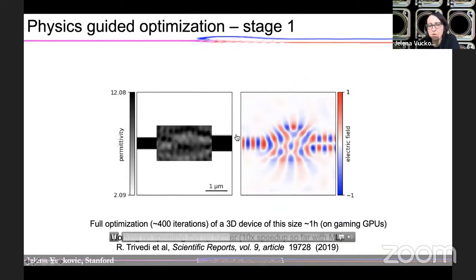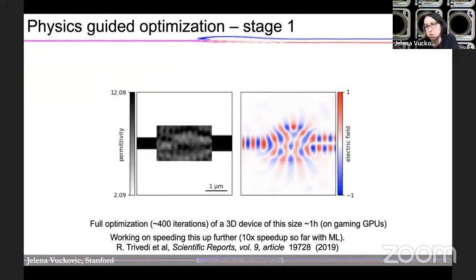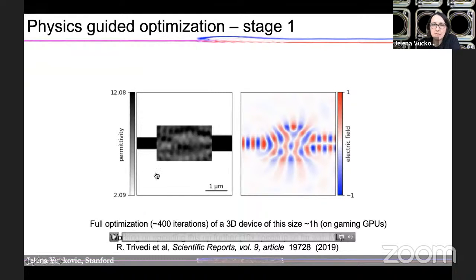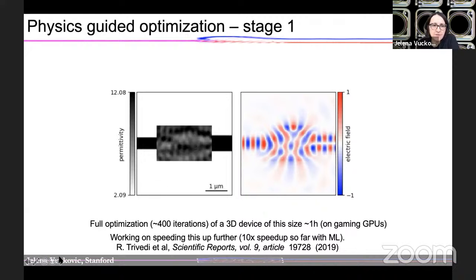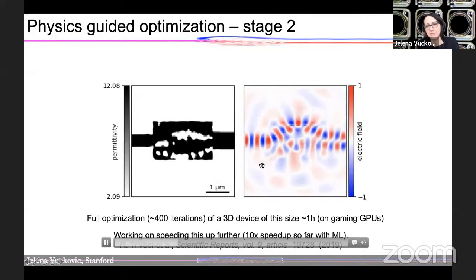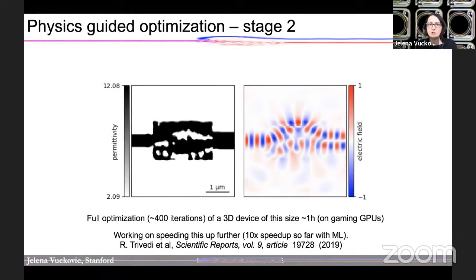You're converting first order mode to second order mode in a very small footprint, like 2 by 1 micron, much smaller than an adiabatic mode converter that people would typically use in photonics. And you see that this works at the end of this first phase, but this is not something you can make because you have continuous change of the refractive index. And then in the second phase of this process, we do binary optimization, where you make something that you can fabricate, and you see that your device at the end actually also performs mode conversion. And we stop when we reach the target efficiency for the function.